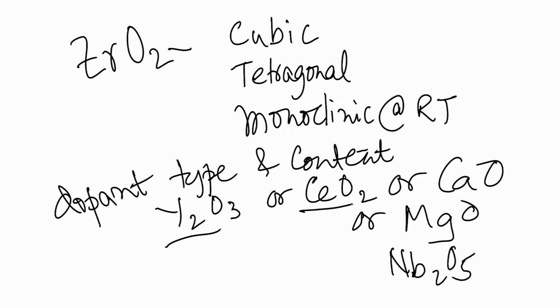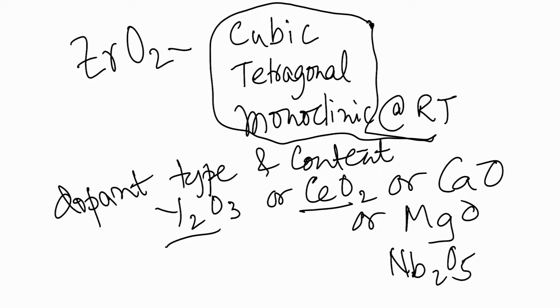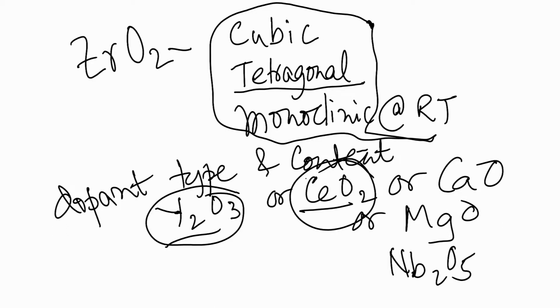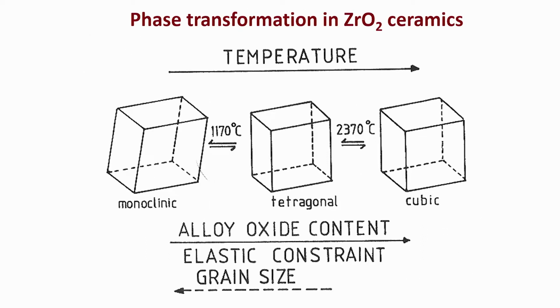These different types of oxides can be doped to zirconia, and this will have an influence on the phase stability of zirconia. Although the tetragonal phase is thermodynamically not stable at room temperature, with yttria doped or ceria doped zirconia, the tetragonal phase can be retained at room temperature. So, there is a compositional effect, and because of this compositional effect the thermodynamic property of the system also changes, and that allows the tetragonal phase to be retained at room temperature. This is one of the important things that one should remember.